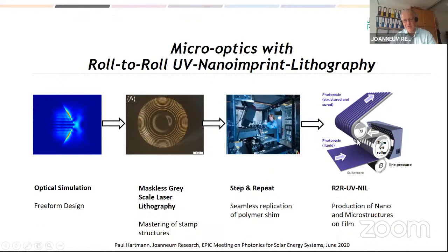So for shims, you need a rectangular size of these step and repeat stamps, and then you can print them on a roll. And you get your optics in a continuous process, which can run at quite high speeds, up to 10 or 20 meters per minute. One of our specialties is that we manage to get this replication in a seamless way on polymer shims. So at least within the accuracy of, let's say, a few micrometers, this is hardly even optically visible.